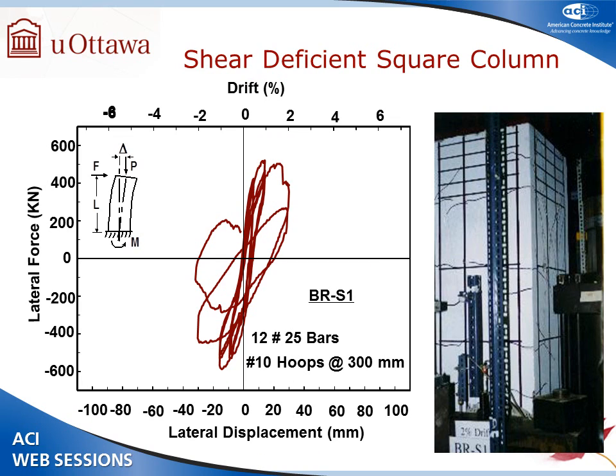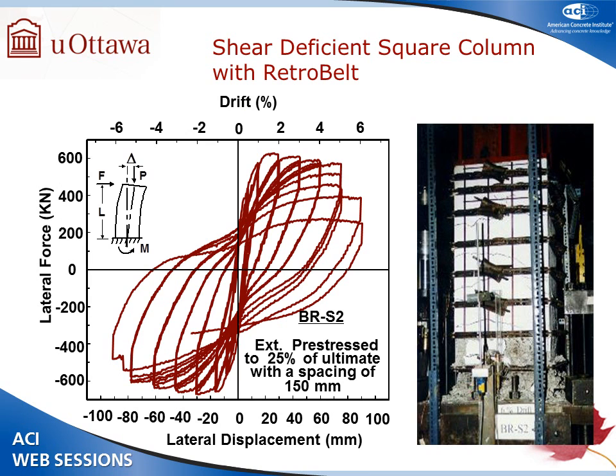This is again a short column, shear dominant, and when we tried to cycle at 2% drift, it couldn't take it. In fact, it failed at the second cycle. So the capacity was essentially 1%. And then there was a huge diagonal tension crack, and it fell apart. And a companion retrofitted column was able to go up to 4% drift without much strength decay, and then sustained 5 or 6% with some strength decay.